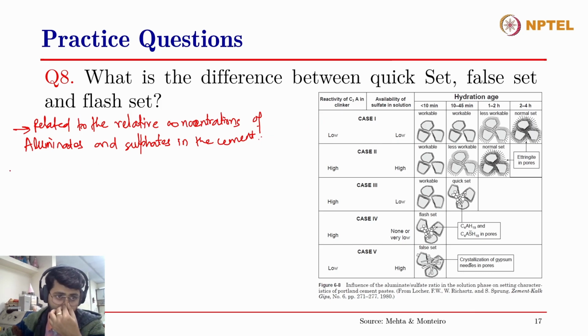So as you know, aluminates, why do we introduce sulfates to cement or clinker? Because why do we add gypsum to clinker? Because aluminates have a tendency to set very quickly. So if we don't provide enough gypsum or source of sulfates, then it will form these hydrogarnet-like structures, and that will lead to a very fast setting of the cement. So therefore, we want to have sulfates in the system.